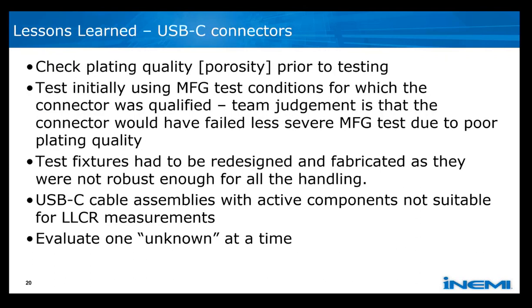So lessons learned. Check plating porosity prior to testing. We were quite diligent, we thought, in checking the plating thicknesses and doing some close examination of the connectors prior to test, but we did not think to check the plating porosity. And we feel confident that if we had, we would have identified that crack in the lead-in point of the contact blade. What I had said before about performing the same MFG corrosion testing as what the connector was qualified for, in this case the class 2A, I didn't speak to it now. We will discuss it in the technical paper.